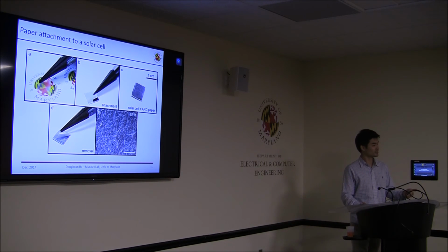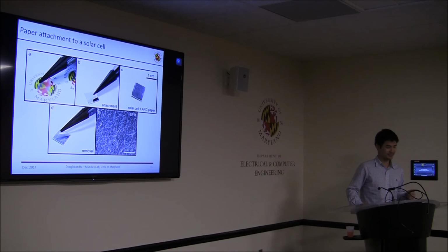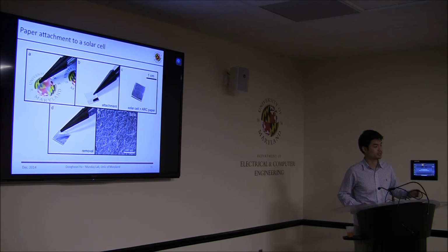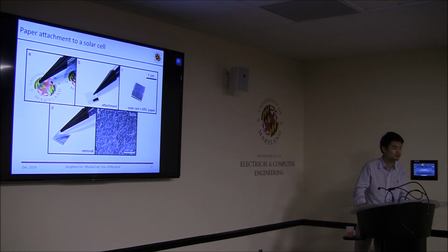So first, I used simple Scotch tape, and sometimes I used water. However, those things didn't work. So I found some literature showing that polyvinyl alcohol can attach the cellulose fibers to some kinds of semiconductors. Also we can use that chemical because its refractive index is exactly the same as the cellulose fibers. It's lucky. It's around 1.5. So it didn't break the gradual index change, and it can hold the papers on the solar cells very well. So yeah, I used the PVA.